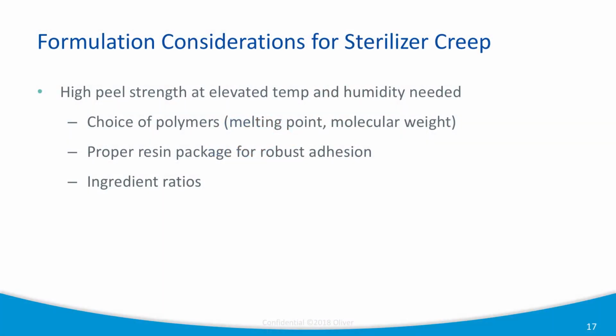The other part of sterilizer creep is maintaining high strength at elevated temperature and humidity, so mimicking EO conditions, which typically might be 55 C and 90 or 95% relative humidity. So again, you have your choice of polymers. Obviously, if it's going to see 55 C, you want the melting point to be significantly above that. And also molecular weight's always important in polymers. As you approach the melting point, there can be something like pre-melting, but high molecular weight resists deformation, and that's helpful. So in this case, high molecular weight is a key component.